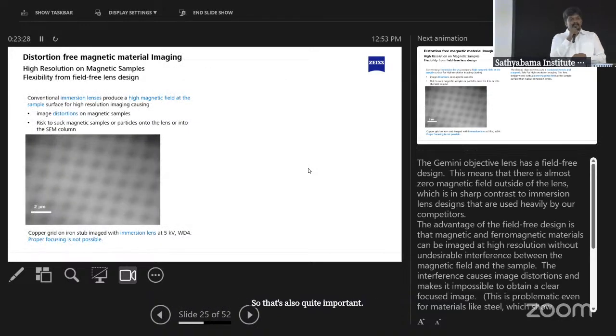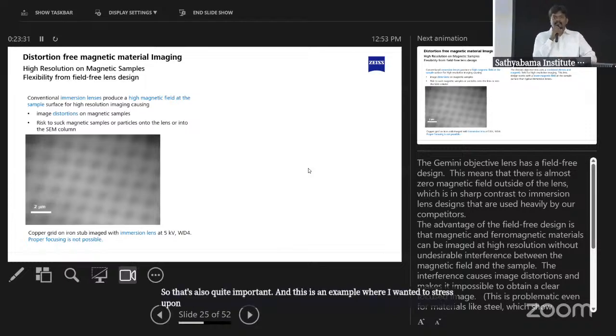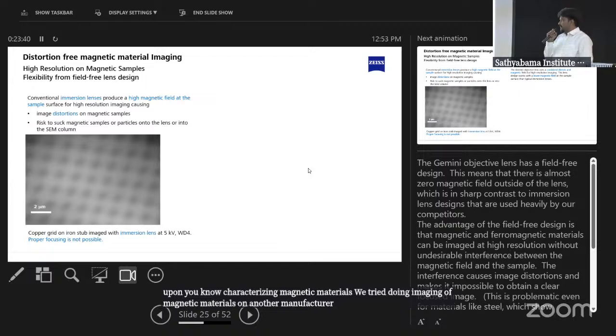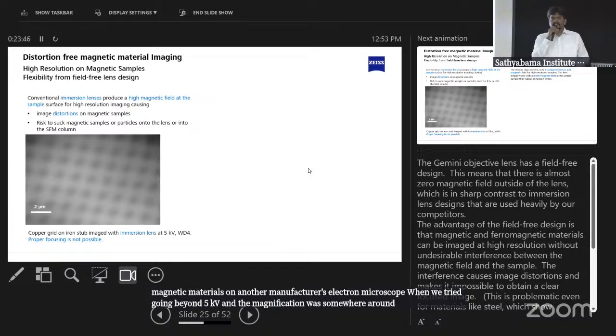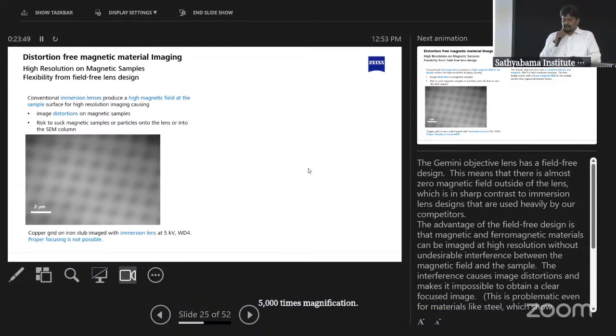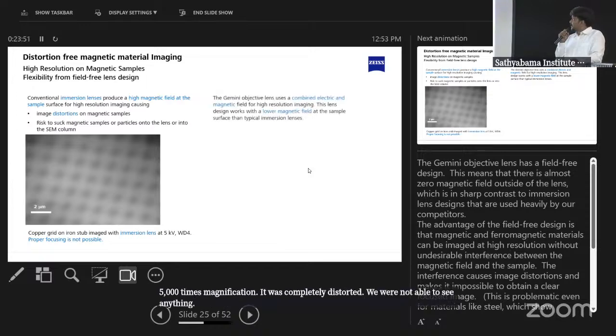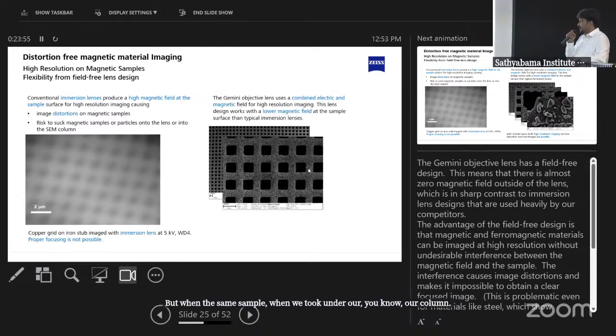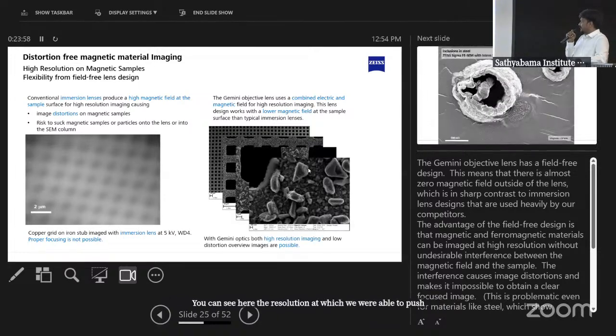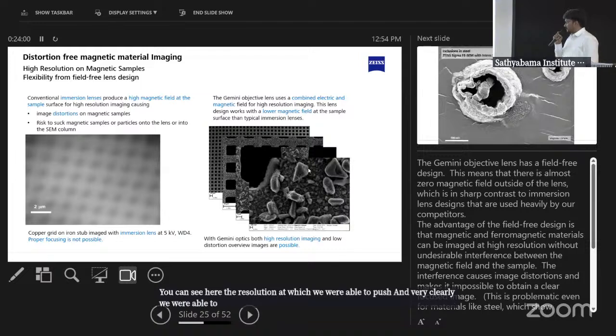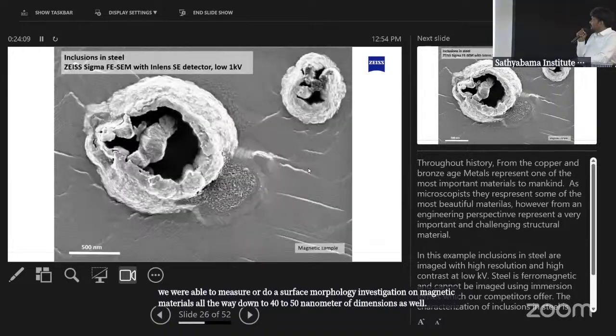And this is an example where I wanted to stress upon characterizing magnetic materials. We tried doing imaging of magnetic materials on another manufacturer's electron microscope. When we tried going beyond 5 kV and the magnification was somewhere around 5,000 times, it was completely distorted. We were not able to see anything. But when we took the same sample under our column, you can see here the resolution at which we were able to push, and very clearly we were able to do a surface morphology investigation on magnetic materials all the way down to 40 to 50 nanometer dimensions as well. That's where we are able to comfortably do it.